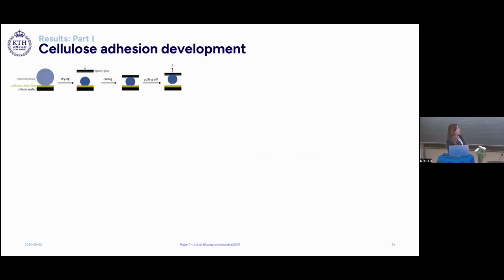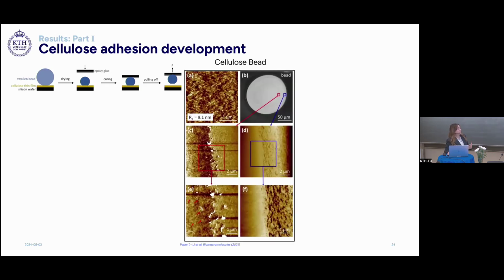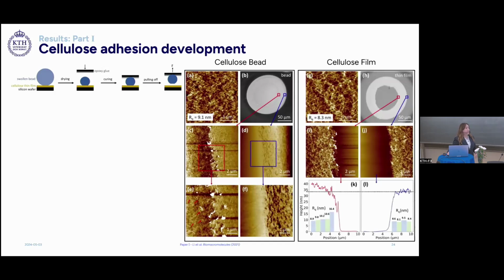To study the adhesion between 2 cellulose materials, we performed pull-off measurements of cellulose beads dried on a cellulose thin film. This was performed by placing the swollen cellulose bead on the cellulose film spin-coated on a silicon wafer, allowing them to dry, and then pulling off the bead and analyzing the surface of the bead as well as the surface of the film after separation.